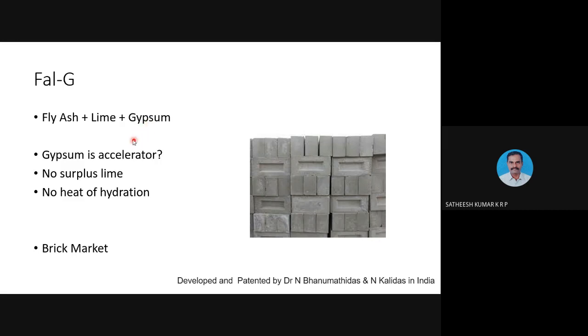The color of these bricks, as you can observe from here, is very similar to the color of the fly ash. It is very dark because we don't have any excess lime here. If there is excess lime, it leads to many other problems. It may lead to cracks because lime has an expansive property, or it may form patches on simple walls.